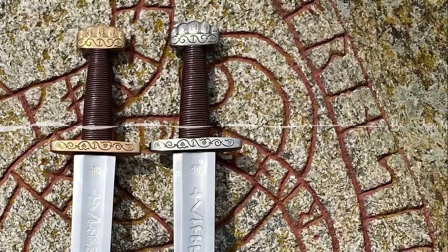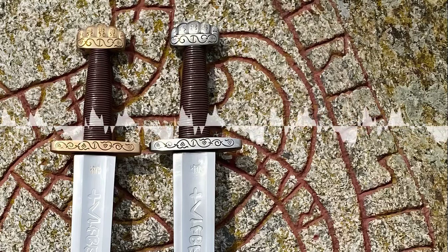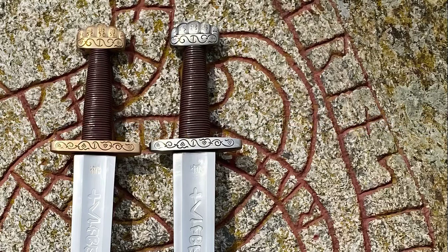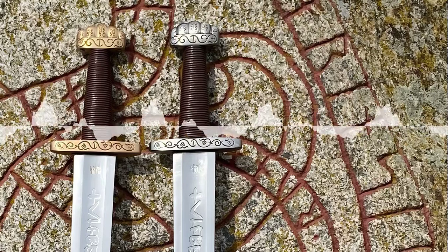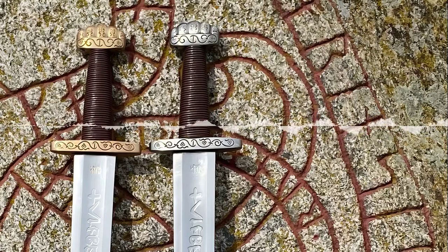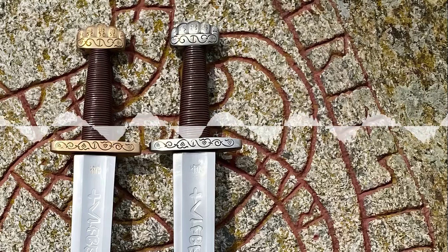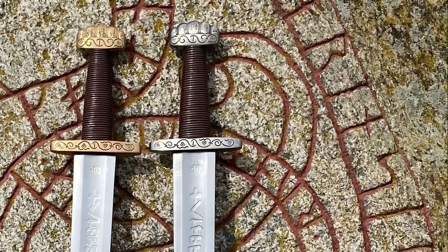The carbon content in Ulfberht blades was between 0.5 and 1.5%, significantly higher than in other swords of the period, often 2 to 3 times as much. That's a massive difference. 3 times as high? Exactly. And because of that, they had a single homogeneous material structure. No more layers, no folding needed. One blade, significantly more robust than most of its contemporaries.